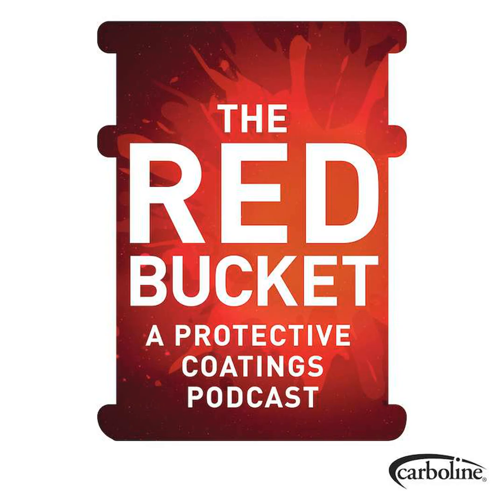So even though in the exposure of that test, you will have that bare metal exposed to salty water and moisture in the air, you will not have corrosion in that scribe, or it will be delayed for some time, because you have zinc and you have the moisture, the electrolyte, to actually help those electrons flow, create that galvanic cell, and have the actual zinc oxidize and not the steel itself.